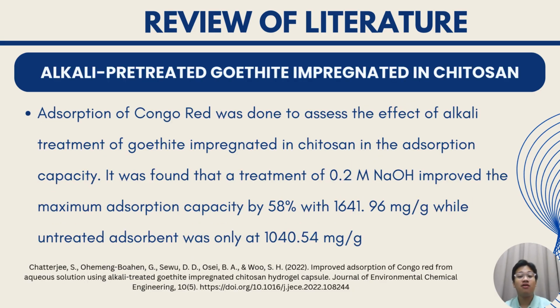Next, a study of Congo red dye adsorption was done to assess the effect of alkali treatment of goethite impregnated in chitosan on the adsorption capacity. It was found that a treatment of 0.2 molar NaOH improved the maximum adsorption capacity by 58%, with 1,641.96 mg per gram, while the untreated adsorbent was only at 1,040.54 mg per gram.